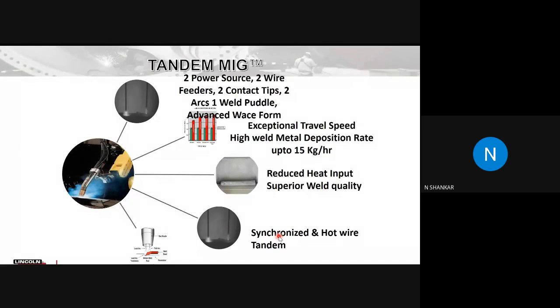For example, if you want to build a small diameter shell using tandem and you're rotating at a very high speed, your weld puddle will tend to flow over before it freezes, because you're rotating the job. So there, it's better to have less heat input. You can use a hot wire tandem. So this is the tandem process increasing productivity.